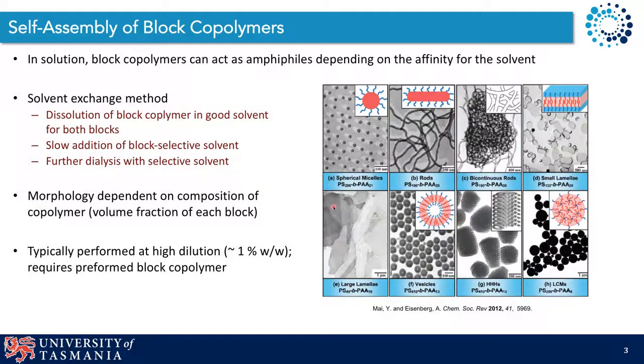We were inspired by the idea of block copolymer self-assembly, which has been well known for an extensive period of time to prepare self-assembled aggregates of a variety of structures, including spheres, rods, lamellae, vesicles, and so on, using block copolymers where one block is selective for the solvent and the other block is a non-solvent. These are typically produced by the solvent exchange method, and the morphology that's produced is typically dependent most prominently on the volume fraction of each block in the copolymer. The drawback of this technique, however, is that the approach is normally performed at high dilution, so scale-up presents a significant challenge.